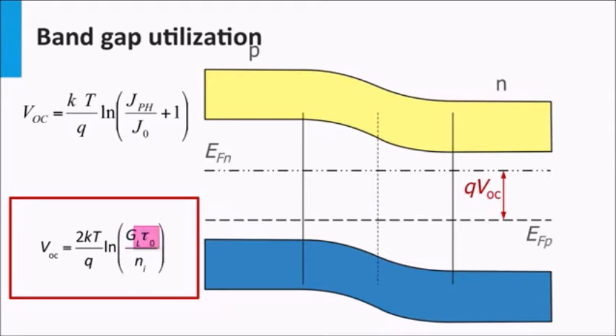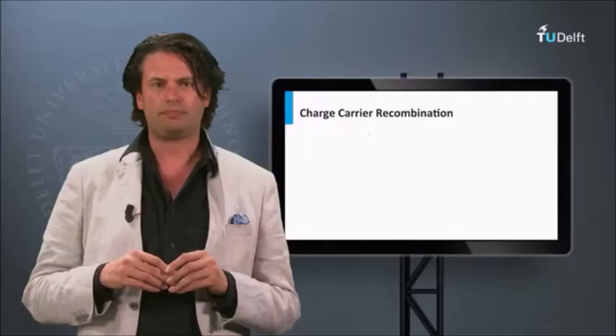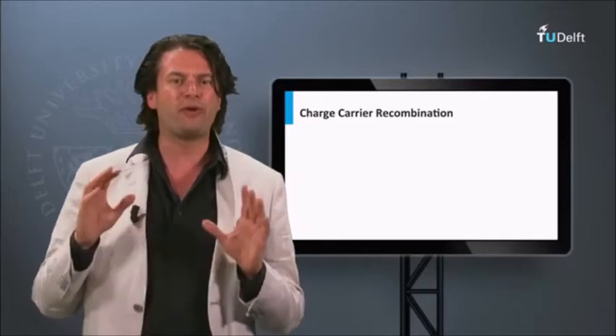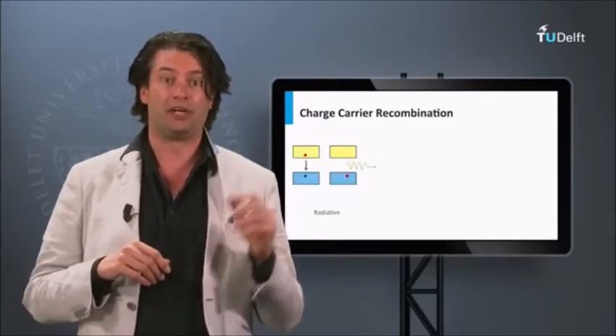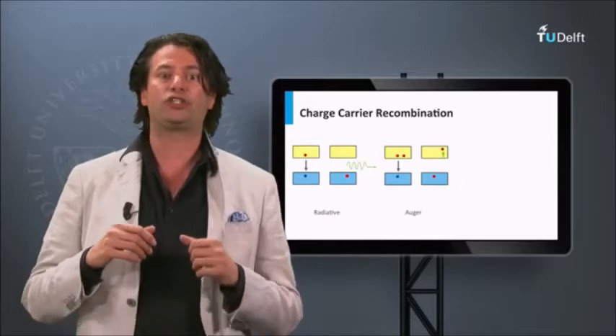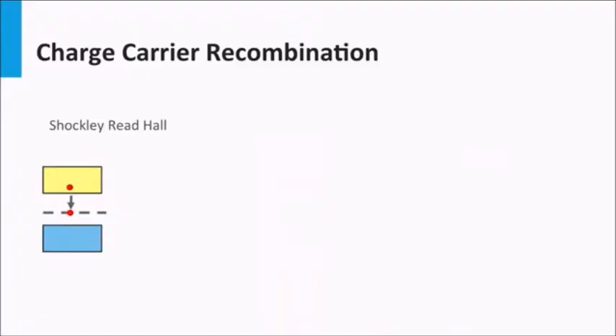Secondly, we see that the lifetime plays an important role. The larger the lifetime of the minority charge carrier, the larger the open circuit voltage can be. Or in other words, the longer the lifetime, the larger the splitting between the quasi-Fermi levels is possible and the larger fraction of the bandgap energy can be utilized. The lifetime of the minority charge carriers is determined by the recombination rate. As discussed last week, we have 3 different recombination mechanisms: radiative, Auger, and Shockley-Read-Hall. Let's start with the last one, Shockley-Read-Hall recombination.